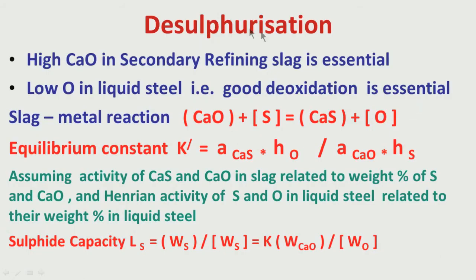Now, what is the desulfurization reaction? The sulfur present in liquid steel will react with calcium oxide, which is present in the slag. So what is the essential requirement? There has to be a good amount of calcium oxide in the secondary refining slag. That means we must add calcium oxide in the ladle so that the slag contains a good amount of it. What is meant by good amount? It has to be about 50%. That means the basicity of the slag, CaO by SiO2, should be very high, maybe more than 3. So the calcium oxide should be at least about 50%, basicity more than 3. This is one important requirement.